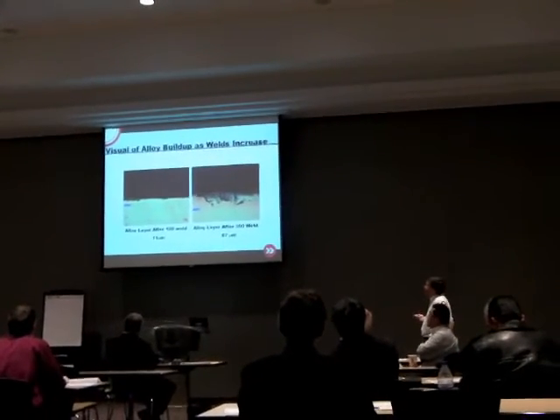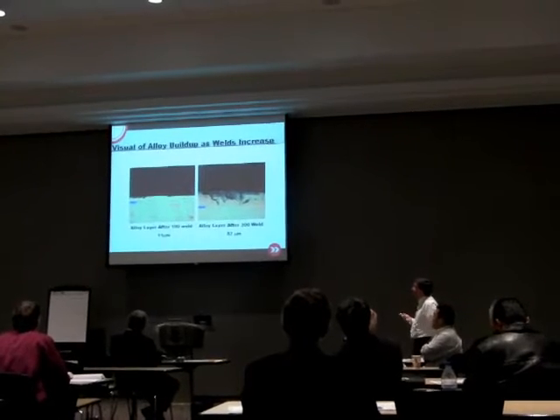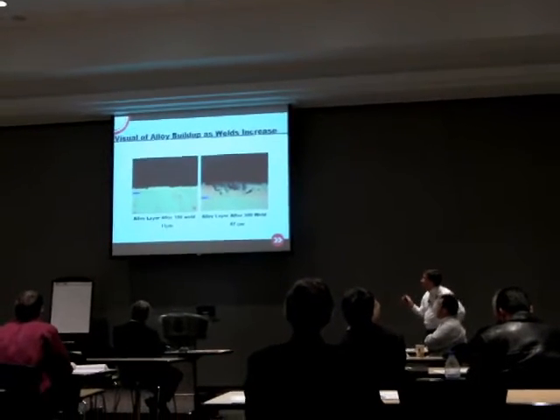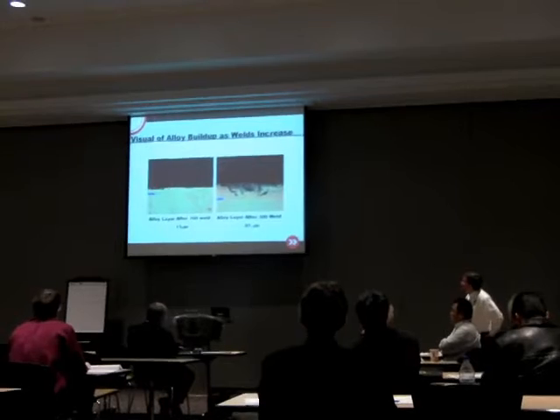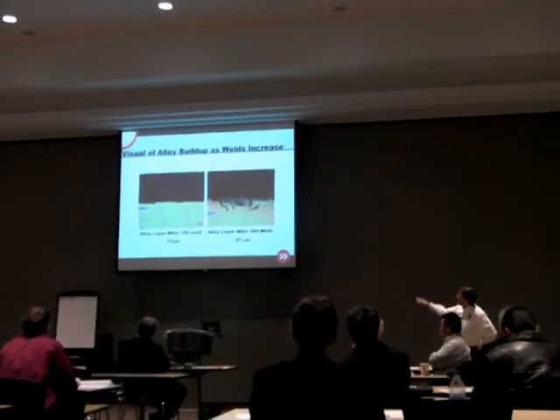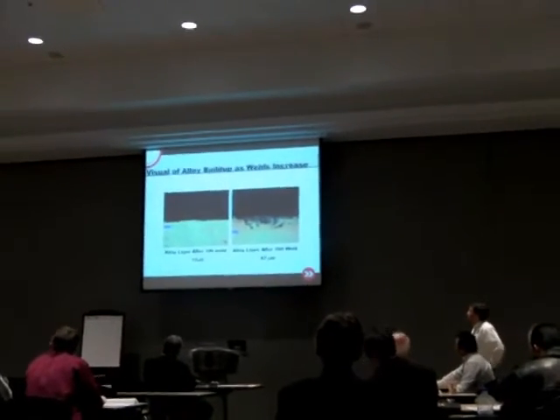What we did was we wanted to break down, we superimposed a photo. After 100 welds, you don't see a lot of change. You see about 11 micrometers of buildup there. Not a whole lot of change there. But after 300, look at the jump. You got 87 micrometers there, and you can start to see some cracking and denting in the electrode face.